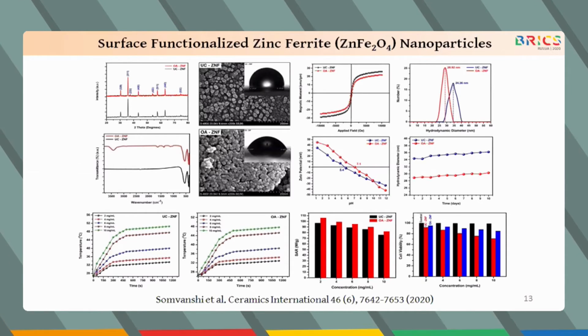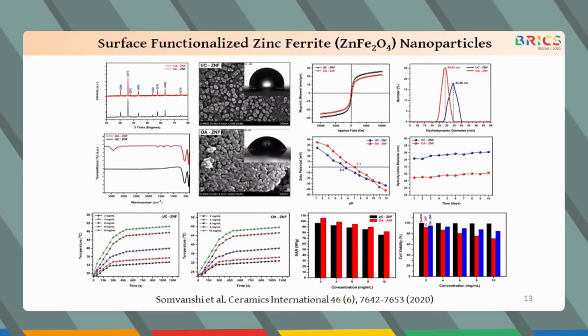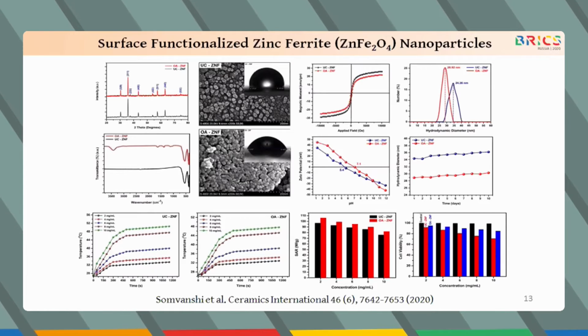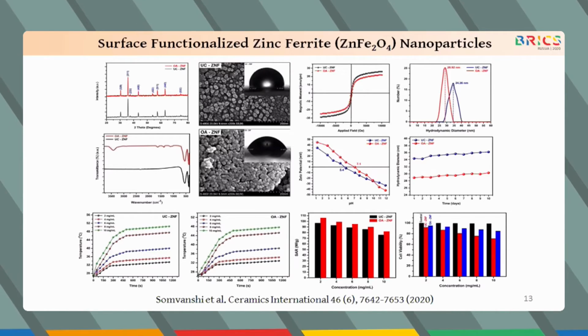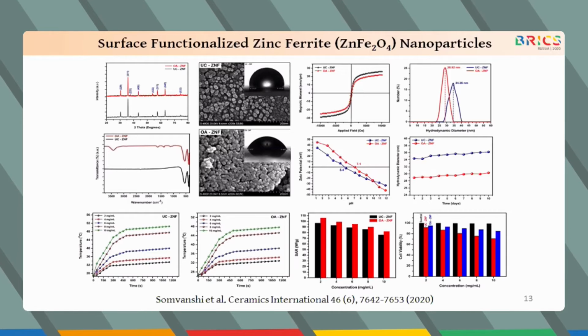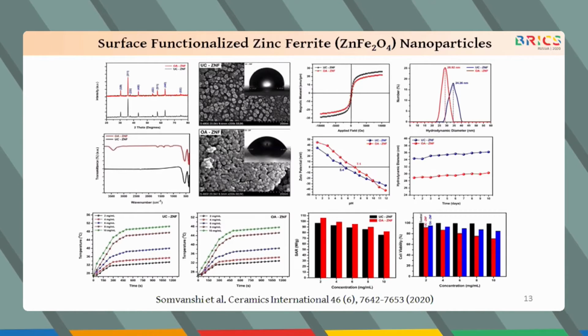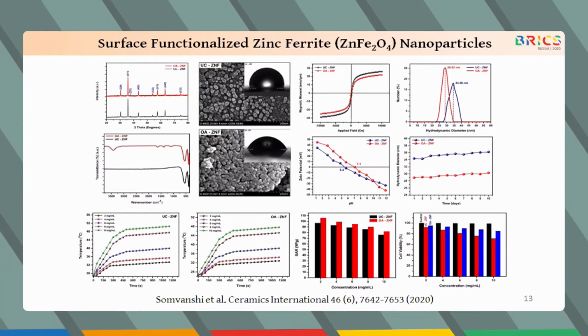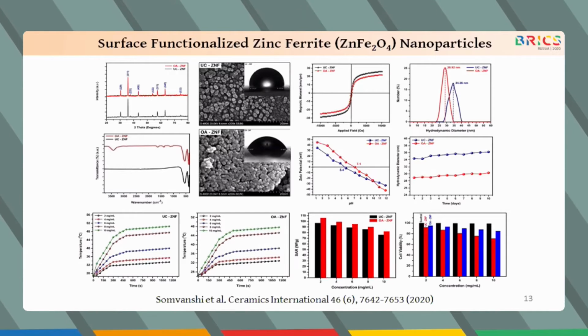The hydrophobic and hydrophilic surface transformation of zinc ferrite nanoparticles was confirmed by water contact angle measurements, as you can see in the inset of the FESEM images. Also, the DLS studies showed the prepared nanoparticles have good stability over 10 days. The VSM plots confirm the superparamagnetic nature of both the samples.